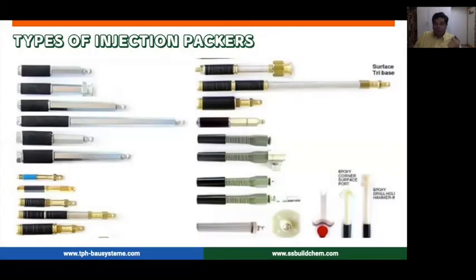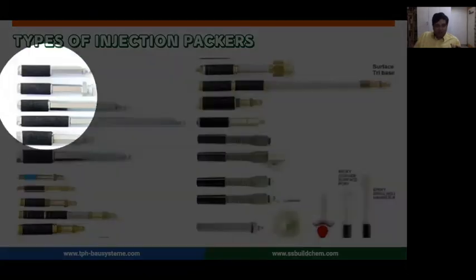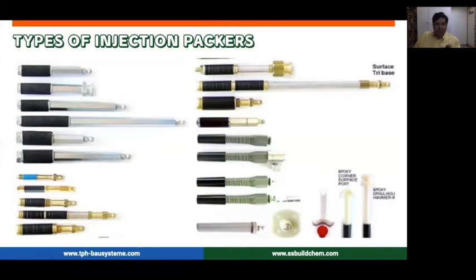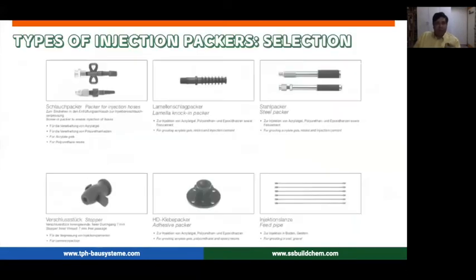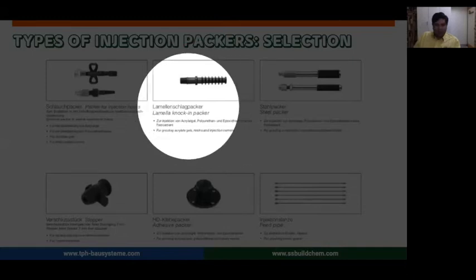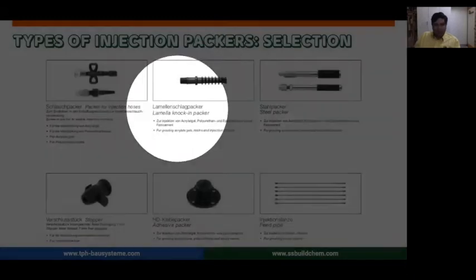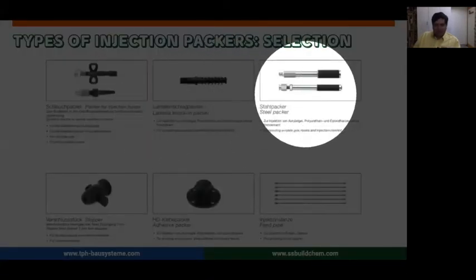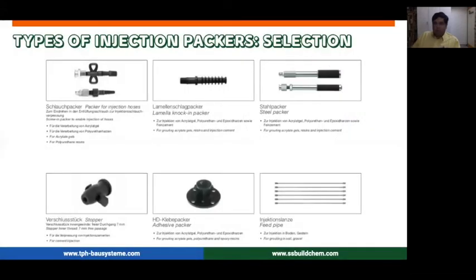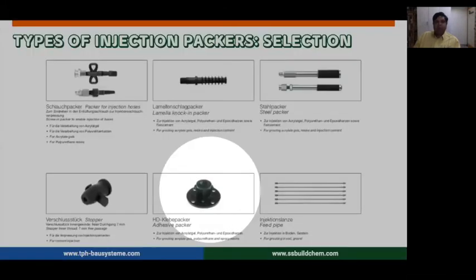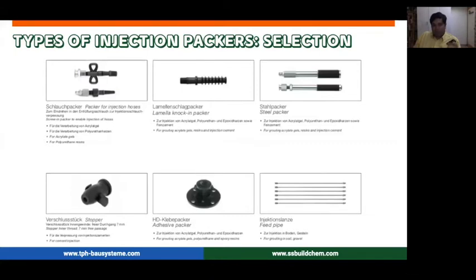Along with pumps, you also need the right packer for the right type of job. If you're talking mostly crack remediation, then mostly we use these kinds of steel packers, along with surface packers if the cracks are very close to the surface. But I would say talk more to us on how to select it. For example, if you're looking only at cement injection, we can use something like these, which we call hammer packers, where you simply knock in these packers. Then these are the steel packers that I was talking about. These are most commonly used. And if your cracks are along the surface and not going very deep, then you can use a simple adhesive packer like this. So modern materials, modern machinery, and modern accessories are what you need to do your job in the right way.